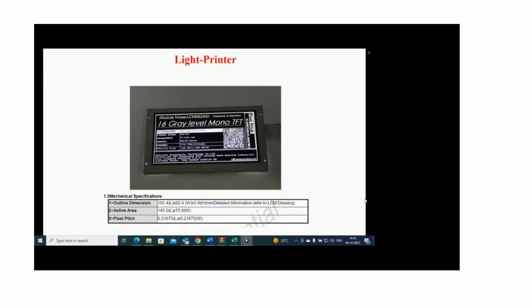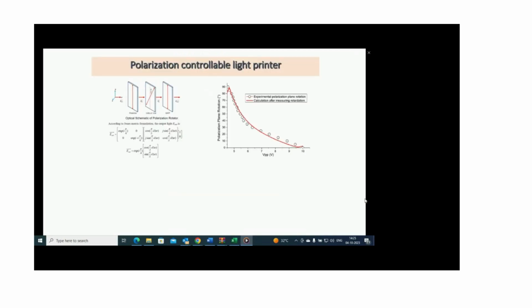As an amplitude modulator, you can use a thin film transistor, black and white, with high resolution. So depending on the light, you can transfer the azo dye to a large angle. Or instead of an amplitude modulator, you can use a polarization controllable light printer. So you can, in principle, rotate the polarization of the light continuously using the polarizer, liquid crystal cell, and quarter wave plate. If you change the voltage, you change the birefringence of the liquid crystal and continuously change the polarization plane rotator.